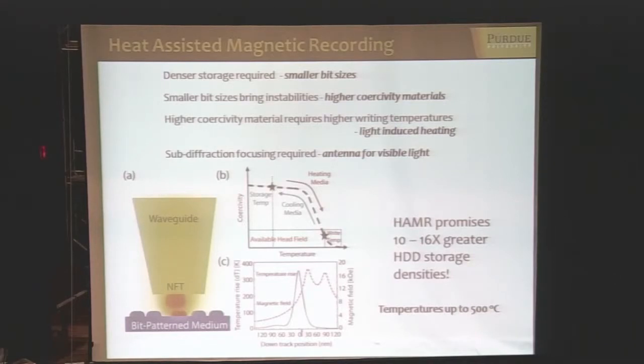So what was suggested long ago is to just locally heat up the certain area, your magnetic bit. When you locally heat it, the coercivity drops, and then you could switch the magnetic moment with a low magnetic field as required, and when you cool it down, you just record that bit of information. It's a well-known technology, but to realize it you need a very small near-field transducer, basically a nano-antenna, to heat it only very locally.